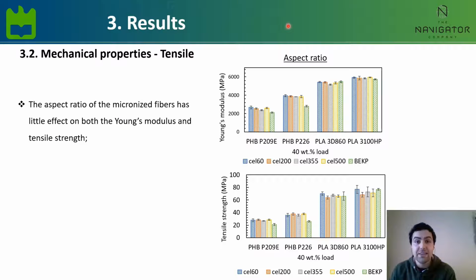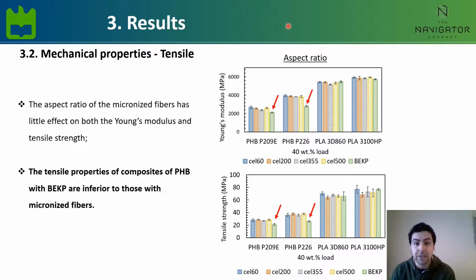On the other side, the aspect ratio of the micronized fibers had little influence on the tensile properties. However, as we can see on the red arrows, the Young's modulus and the tensile strength of PHB composites with bleach eucalyptus kraft pulp are inferior to those composites with micronized fibers, and this means that micronization may in fact be a viable method to improve some of the properties, especially in composites with PHB.